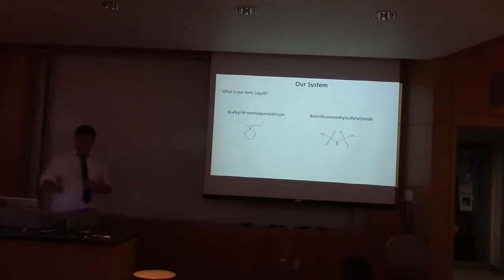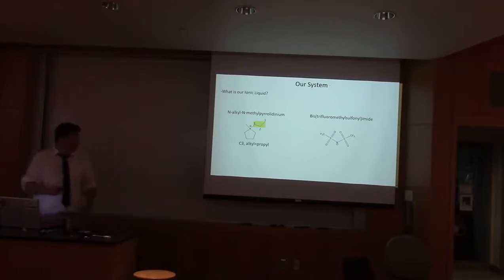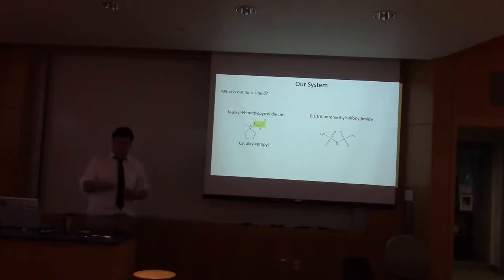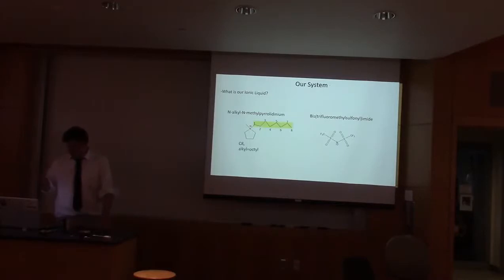Now I'd like to move into specifically what my system was and what we were looking for. I'll begin by describing the ionic liquid I was working with. I worked with an N-alkyl N-methylpyrrolidinium based cation, this one over here, and a bis-trifluoromethanesulfonimide anion, sorry, I might have flipped those. We chose to use 4 different ionic liquids. The difference between the 4 was the length of the alkyl chain within the cation: the propyl, the butyl, the hexyl, and the octyl.